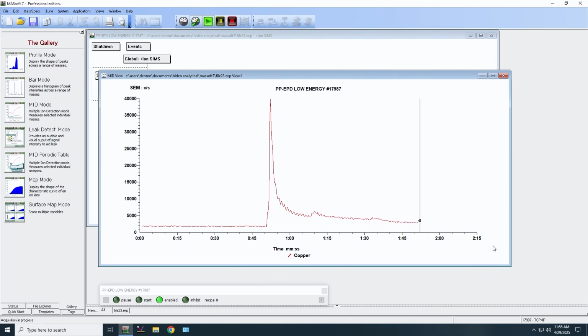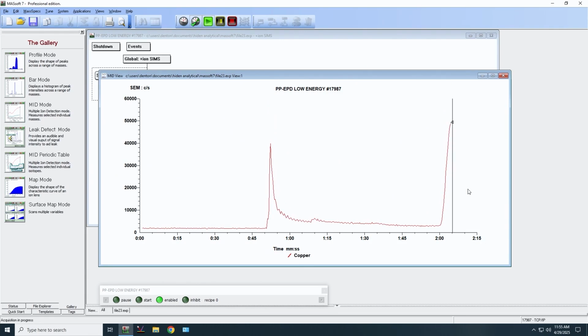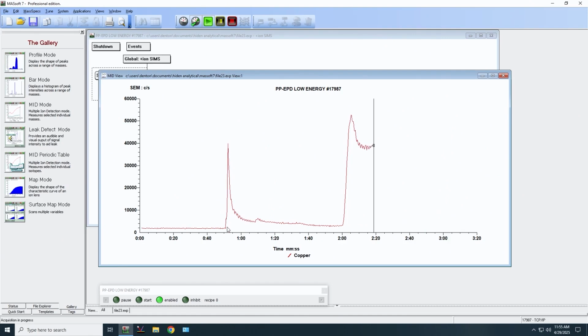So this stack starts with a silicon layer 120 nanometers thick. At these conditions of 600 volts and 230 milliamps, it etches through about a micron of material in about 10 minutes. So that's going to go through the 120 nanometers of material. It went through from about 50 seconds up until 2 minutes, so that's 1 minute and 10 seconds to go through 120 nanometers. And now we're seeing the real copper signal.